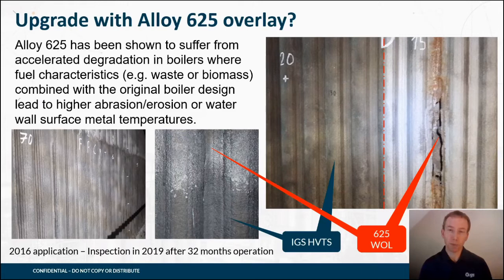And what you can see in the photograph is an example of a waste to energy boiler where they were burning household waste. This is an area just above the refractory line, and in particular in the membrane in between panels, where you tend to have a wider pitch between the tubes. And so the metal in the center of that membrane is at a higher temperature, and that's because it's further away from the cooling effect of the water wall tubes. And in that zone, you can see the installed 625 weld overlay has rapidly broken down and actually created a hole through the membrane wall. In the zone where we have the thermal spray installed, this has a higher temperature capability and so is resisting that environment. So alloy 625 is naturally a system to think about, but there are alternatives in the marketplace that can outperform alloy 625 and provide a viable alternative as a solution in these environments.